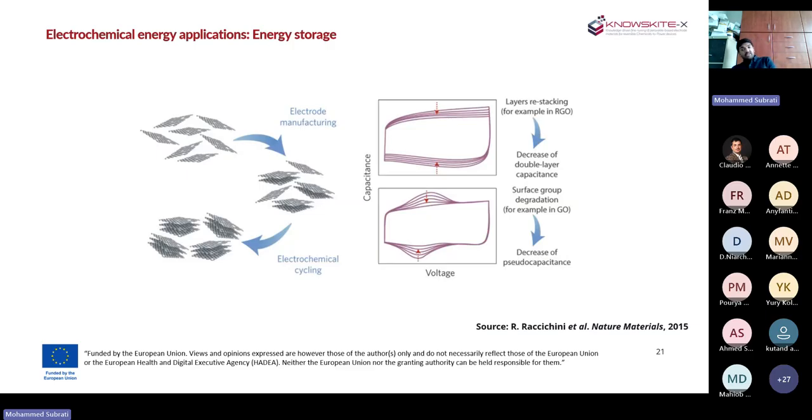Okay, what about graphene oxide? Graphene oxide has the oxygen functional groups, so redox sites, very nice. But what about their stability? They are not stable. This is why after multiple cycles, you tend to lose oxidation, reduction, oxidation, reduction. You tend eventually to reduce graphene oxide, ending up with this rectangle-like shape on top, I mean the shape of the cyclic voltammogram of reduced graphene oxide.